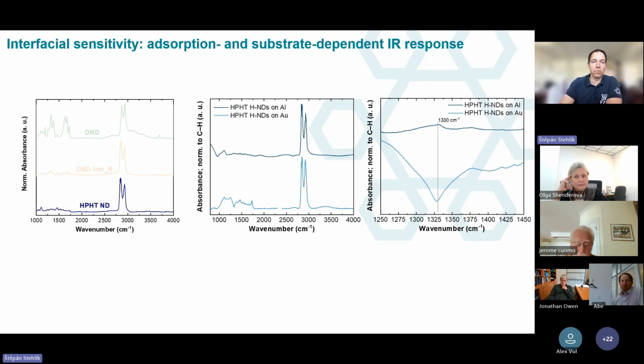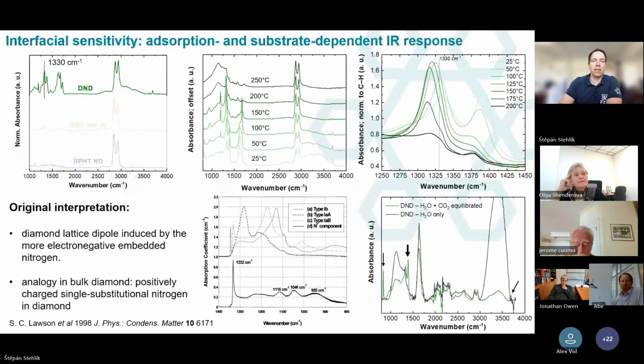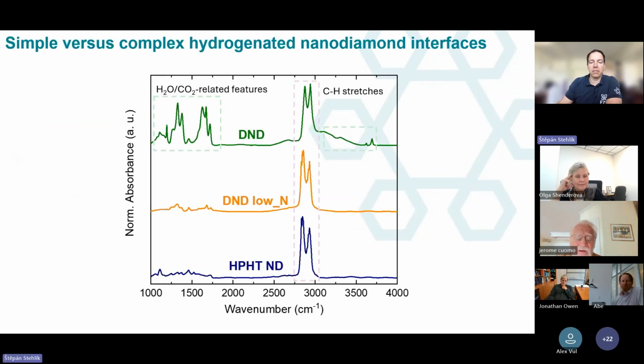Yeah, and I also wanted to point out that here in these two low nitrogen samples, we saw a very similar CH stretching pattern, and a very different pattern actually on the DNDs. So it looks like the nitrogen also somehow modifies the stretching of the CH. And I think the frequencies could also be assigned to particular CH, like CH1, CH2, CH3 on different facets. So it should also be sensitive to the prevalence of the facets or the shape of the particle.